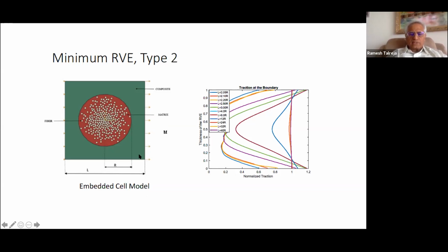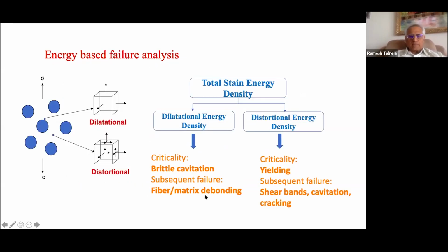So if I reduce the size of this outer region, you see though this is the reduced size, it gives a non-uniform result. That is, if I apply uniform displacement, I get non-uniform traction. I keep increasing the size until I get to this equality of uniformity in both cases. So those are details you can find in papers if you wish.